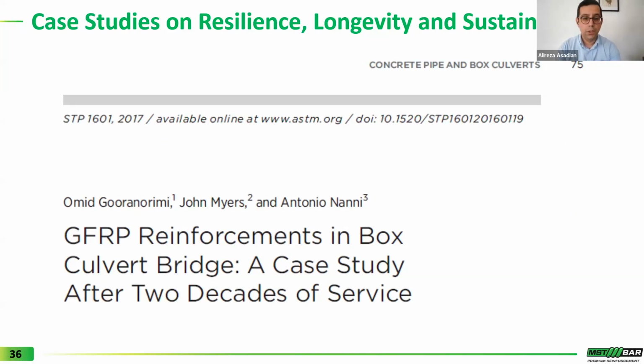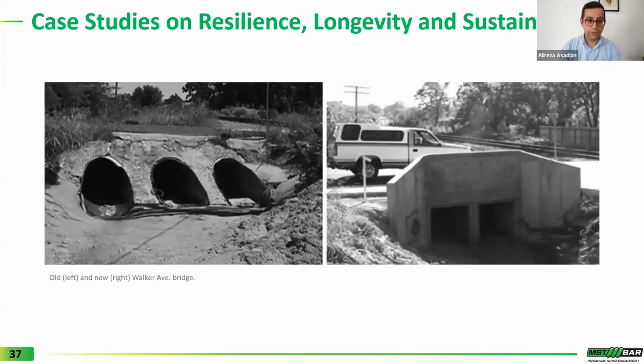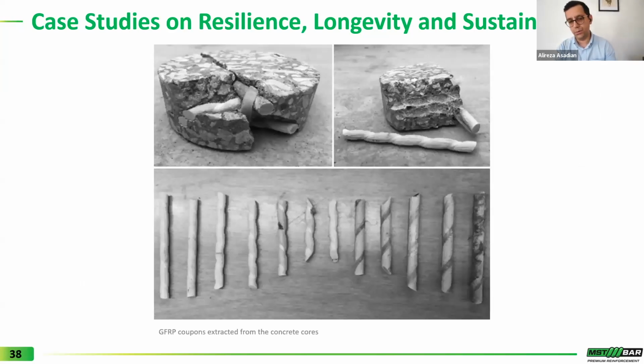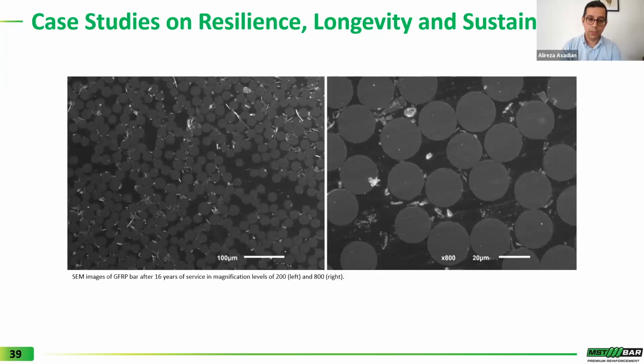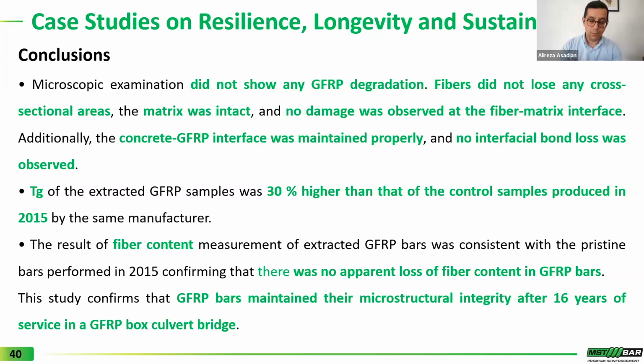in this application. Another study done by Professor John Myers and Professor Antonio Nanni is on the GFRP reinforcement in a box culvert after 16 years of service. You see here a picture of an old culvert and a new culvert, and again, similar to other case studies, they have taken some real core samples from the culverts to do the durability studies. They have done SEM image analysis, and similar to the previous project, they concluded that the microscopic examination did not show any GFRP degradation, and fibers did not lose any cross-sectional area. The matrix was intact. No damage was observed at the fiber matrix interface. Also, the concrete GFRP interface was maintained properly and no interfacial bond loss was observed.